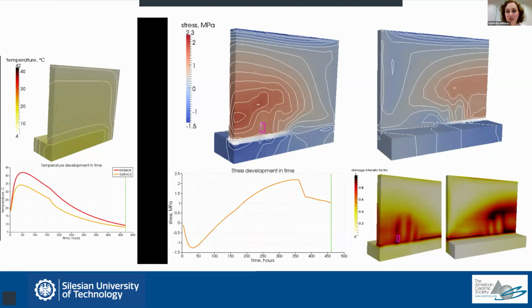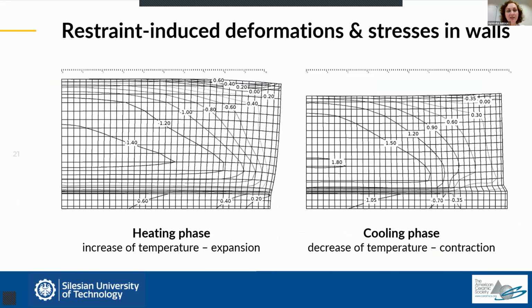So in the bottom of this slide in the simulation, you see the cracks that are forming. And as you have noticed, the pattern of these cracks correlates with the observed pattern in the real walls. So just to summarize, the situation looks like that. We can divide the behavior of such a wall into two phases.